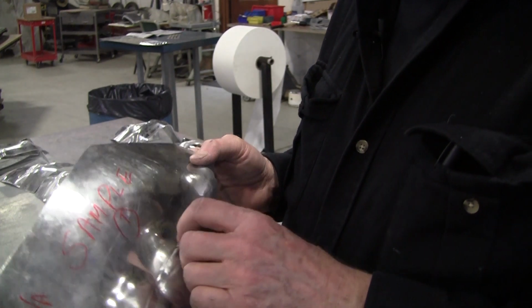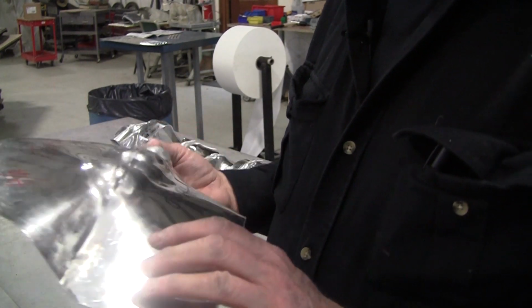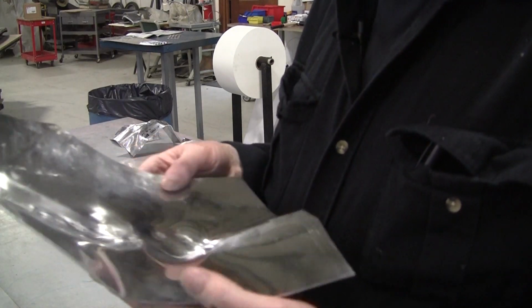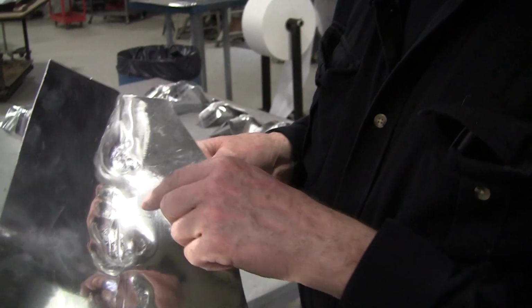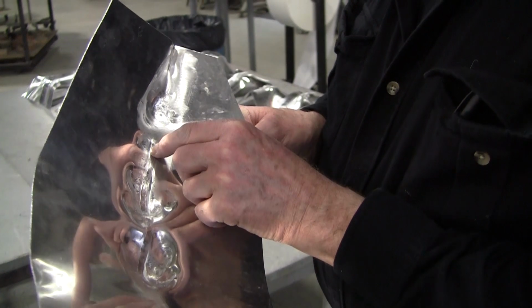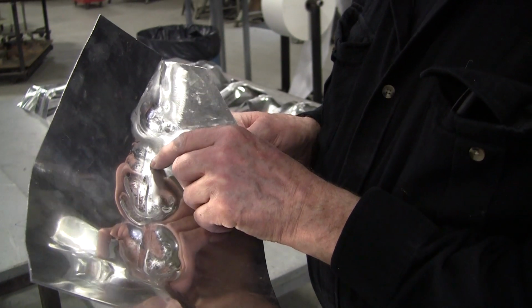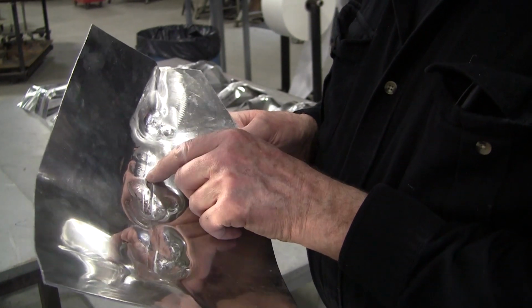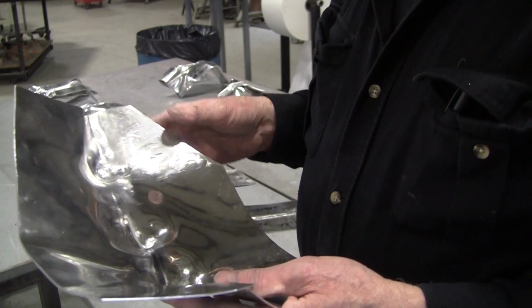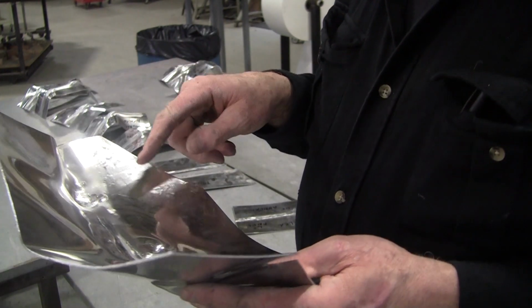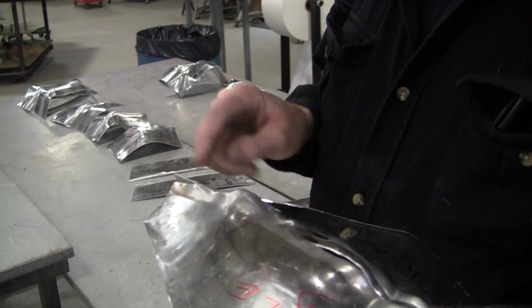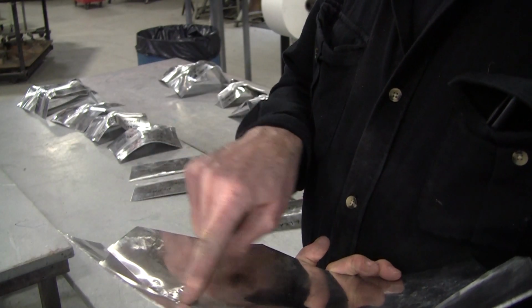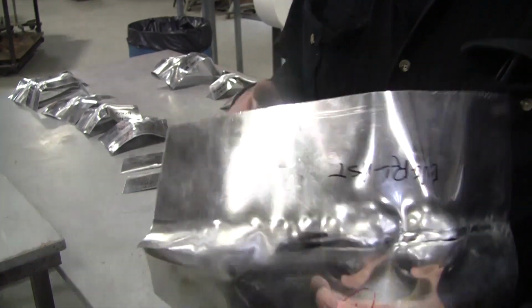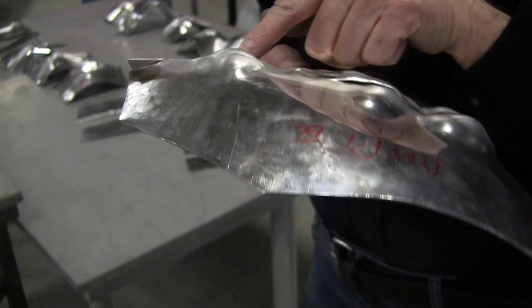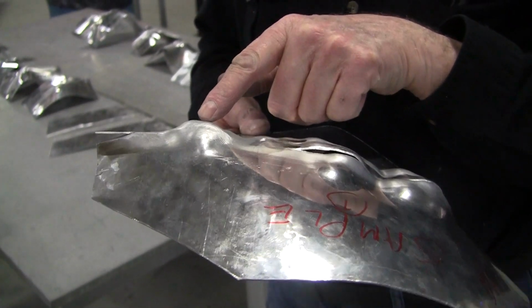It cracked adjacent to the weld. And the issue was I didn't grind it properly, and I left just a hint of where the edge of the weld was on the back side. And that was a weak point. So after a couple days or so, there's still a little bit left on that sample, I'll grind those spots down and I'll do the torture tests, and there it is, and it didn't break right there.